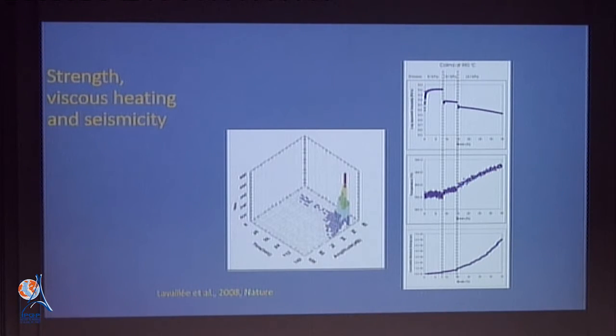But you can see also on the bottom part of the scale, the numbers of acoustic emissions described as an effective energy of acoustic emissions, and you see that it starts to ramp up non-linearly. The fact that we can observe the statistics of what these things do acoustically in the laboratory, and we can also observe that they fail catastrophically in the laboratory, you know where I'm going, right? I mean, in principle, if we understand it well enough in the laboratory, we have at least a shimmer of hope that we can understand the equivalent seismic signals pre-catastrophic failure in actual volcanoes.